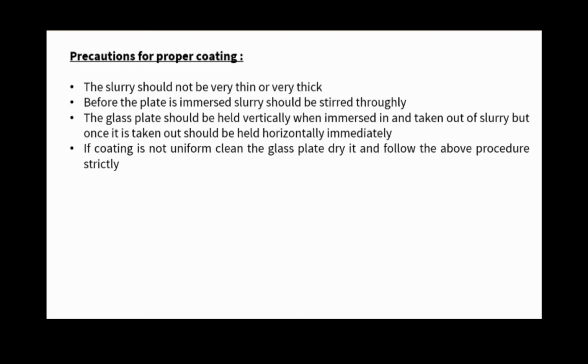There are some precautions which we have to take care of while preparing a TLC plate. What are they? First, the slurry should not be very thin or very thick. Before the plate is immersed, the slurry should be stirred thoroughly. The glass plate should be held vertically when immersed in and taken out of the slurry, but once it is taken out it should be held horizontally immediately. If the coating is not uniform, clean the glass plate, dry it and follow the above procedure strictly. Okay, after that